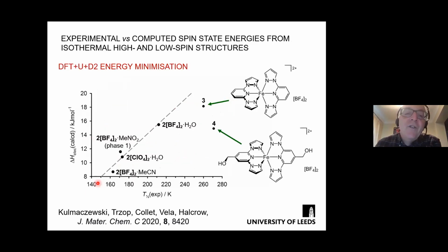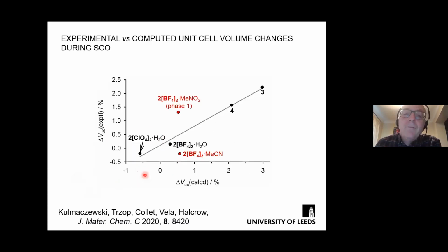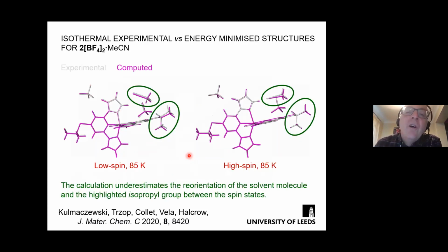The calculations reproduce the thermodynamic spin state changes for this material properly, but they don't calculate the correct crystal structure. And I should say this is not high spin, low spin structures now. This is experimental and calculated crystal structures of this material. And you can see where the differences are.